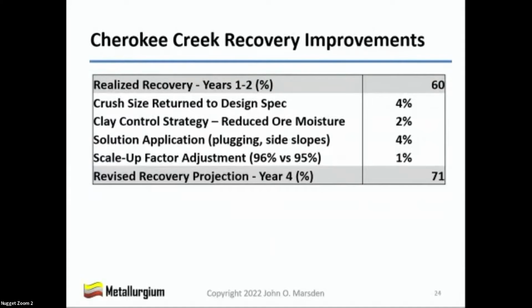So she took steps immediately to get the crush size back on track, and that took a little bit of money to get the crushing plant up to speed. She implemented a clay control strategy. One of the problems they'd had was that they had regions of the heap that had higher clay than other regions, and she got a little bit out of that. She improved the solution application, and at the end of doing that, she figured out that her scale-up factor was a little overly punitive, and she adjusted that to 96%. And her revised recovery projection for year 4 was 71%.